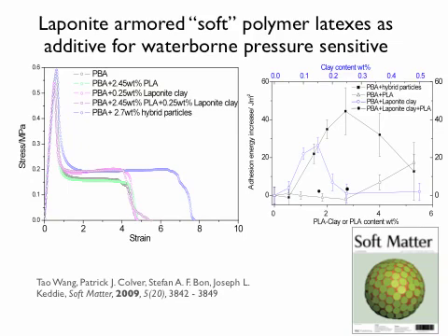And how does a sticker work? Well, basically, it's a gooey mess, right? So a good waterborne sticker material for labels would be a polybutyl acrylate latex. A polybutyl acrylate latex has a Tg of minus 54 degrees Celsius. So you dry these particles out, they stack on top of each other, and it just becomes a really sticky polymer film.